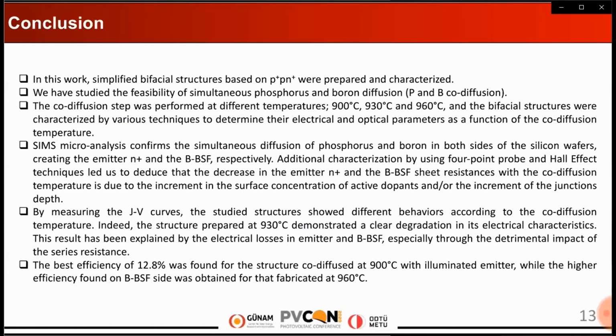So we finish with a conclusion. In this work, a simplified bifacial structure based on P plus P N plus was prepared and characterized. We have studied the feasibility of simultaneous phosphorus and boron diffusion. The co-diffusion step was performed at different temperatures, and the bifacial structures were characterized by various techniques to determine their electrical and optical parameters as a function of the co-diffusion temperature. Secondary ion mass spectroscopy microanalysis confirms the simultaneous diffusion of phosphorus and boron on both sides of the silicon wafers, creating the emitter N plus and the boron BSF, respectively.